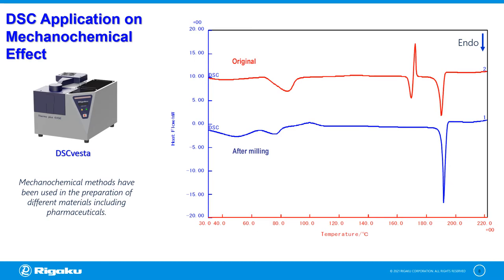However, in the pulverized material, only the endothermic peak at 180°C due to melting is observed. Also, the dehydration behavior differs from the original material. The external application of mechanical energy causes physical changes known as the mechanochemical effect, which may cause differences in measurement results.